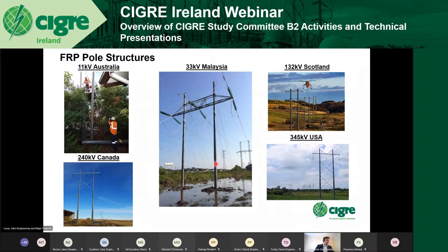Moving on to 33 kV in Malaysia, probably a good example of where, if it was wood poles, you could have a rot issue. And from a steel structural point of view, you could have a corrosion issue. So there's an improved performance with the composites in those situations. 132 kV in Scotland, which was a fairly dramatic project. They actually used the sky crane helicopter to lift in the complete structures, so quite a rapid construction. So the lightweight nature of the material was quite useful in that situation.